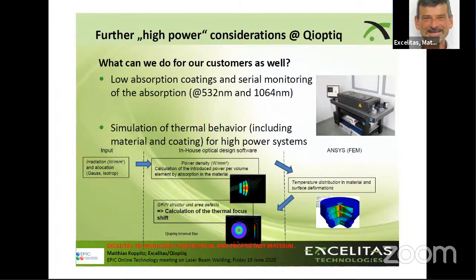So we know the material, we know the absorption from the material, we know the absorption of the coating, and by simulation we can calculate thermal focus shift, and we can decide, for example, if it's really needed to have a water cooling system to cool down, or if we use a very good fused silica with low absorption, then maybe we do not need a water cooling system.